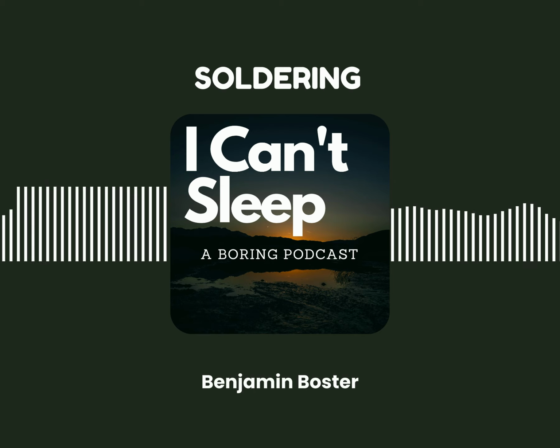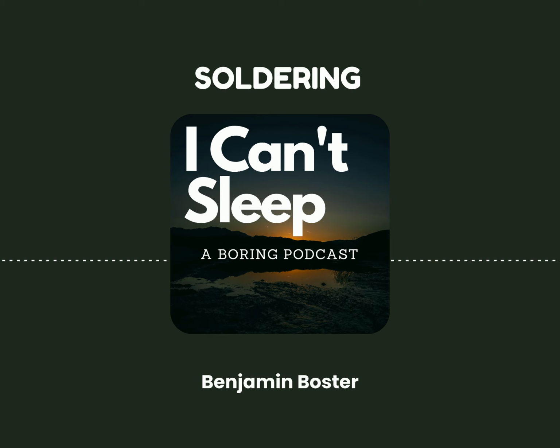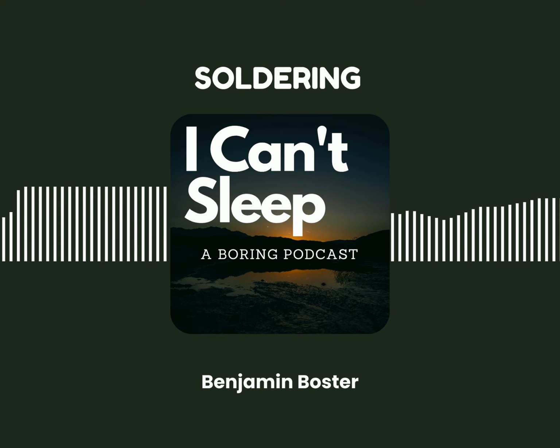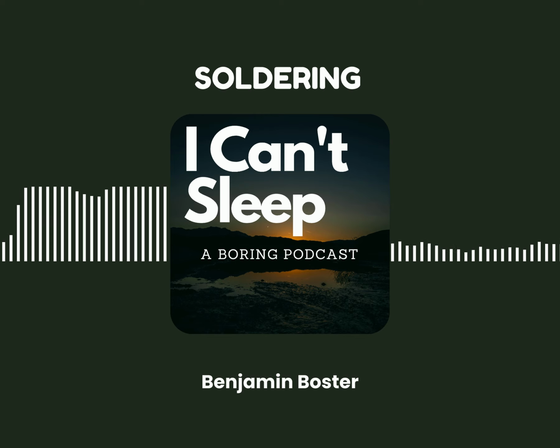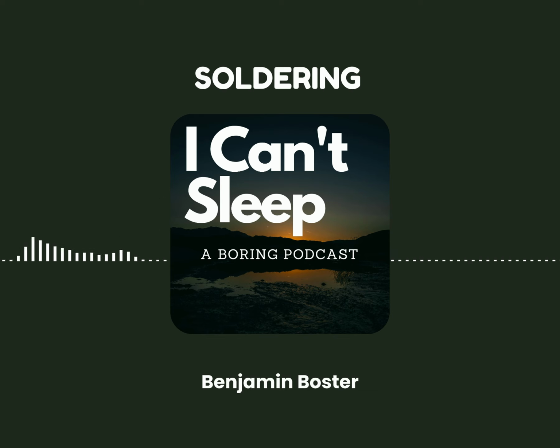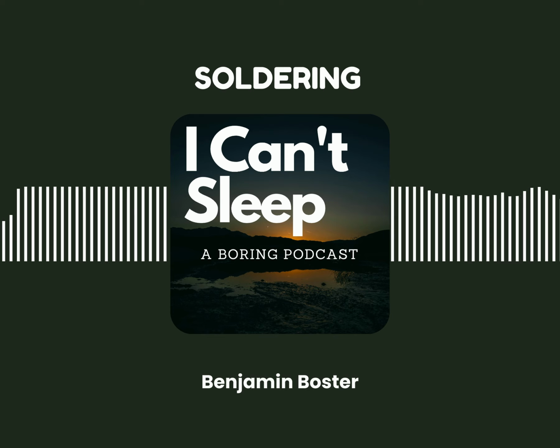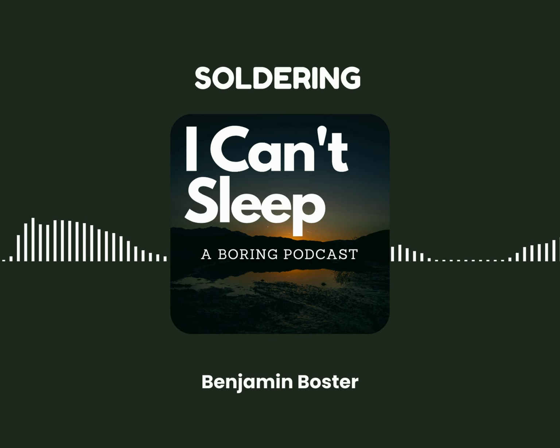Photonic soldering is a relatively new process that uses broadband light from rapidly pulsing flash lamps to solder components to a circuit board. Energy consumption is approximately 85% less than that of a reflow oven, while the throughput is higher and the footprint is smaller. It is similar to photonic curing in that the components to be soldered are heated while the substrate remains relatively cool. This enables the use of high-temperature solders, such as SAC 305, even on thermally fragile substrates such as PET, cellulose, and fabrics.